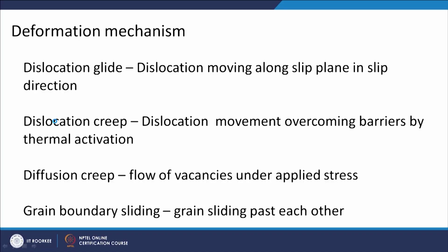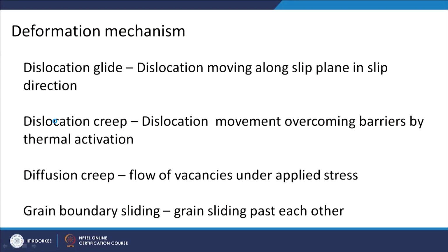Then, because you are at high temperature, diffusion based deformation can also take place. This is what we call diffusion creep. So, flow of vacancies takes place under the applied stress. So, this is another very important mechanism at high temperature. Another very important mechanism you will see is called grain boundary sliding, where the deformation is not taking place within the grain.